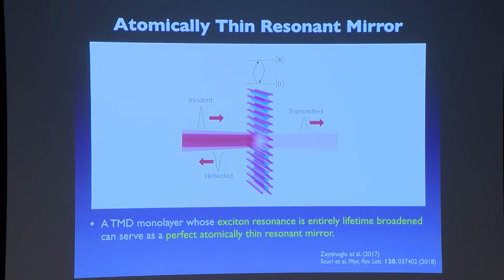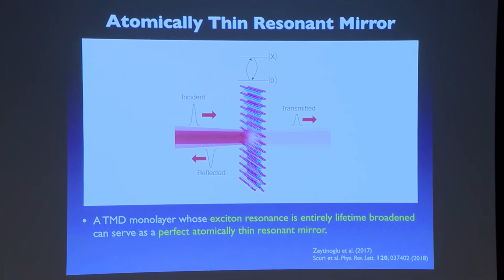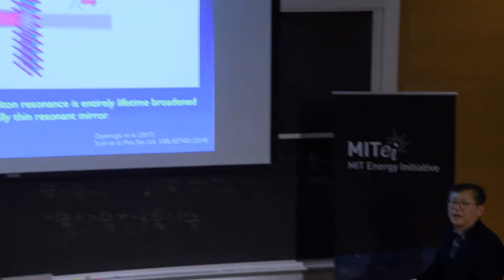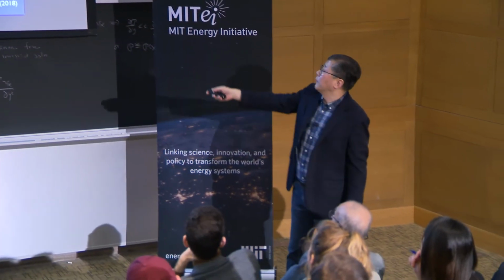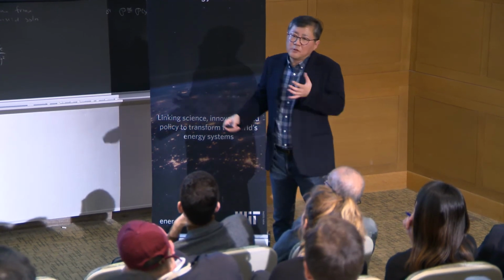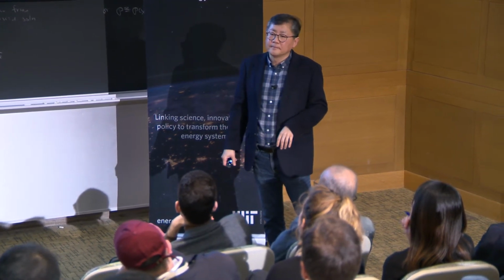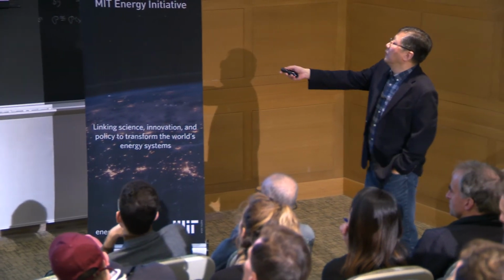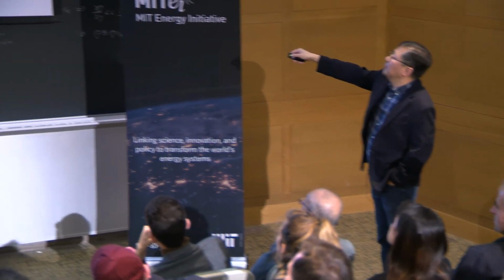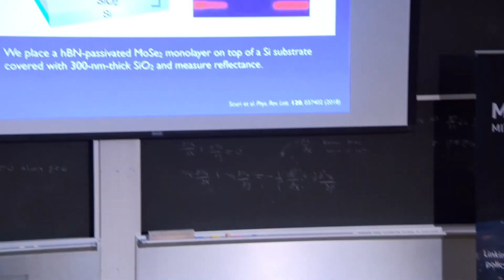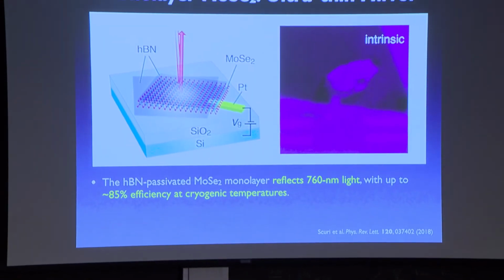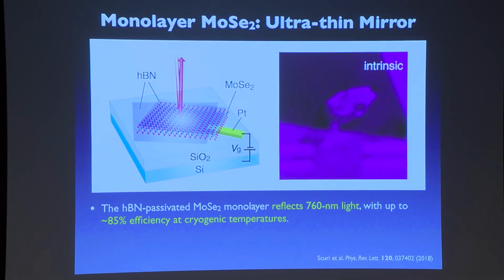But of course, all that perfection is not easy to achieve. Even for a benchmark system like gallium arsenide quantum wells, which is another technical jargon, but it is one of the systems that people have studied for a long time to perfect the material quality, when they measured the reflectivities like this, they were usually about 3 to 4%. So what we decided to do was to spend a lot of time perfecting the properties of these atomically thin semiconductors. What happens if you shine the laser light? It turns out that if you just do that at cryogenic temperatures, like below 100 Kelvin, up to 85% of the light gets reflected back immediately.